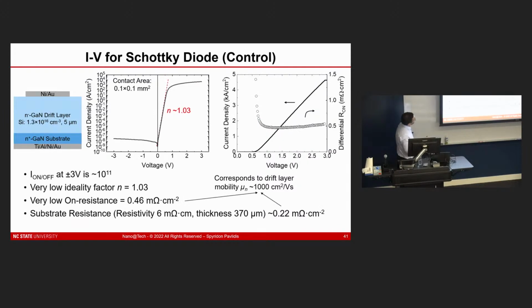So the best way that I can really convey to you how good the surfaces are now with the improved processes that we have is through this Schottky contact, because as we know, Schottky contacts are very, very surface sensitive. And so this is a control Schottky diode that we make on that same wafer that's gone through all these processes. In this case, it's Schottky contacts, so there's no implanted region here, but it has gone through the anneal. And we can see near ideal Schottky barrier contact, Schottky behavior here as well.